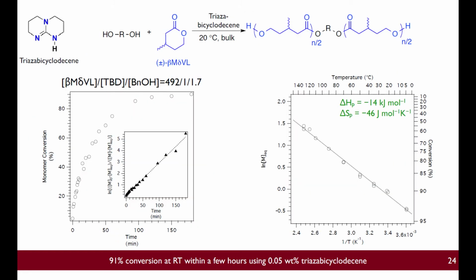Debbie Schneiderman in my group ended up taking beta-methyl valerolactone, and with this organocatalyst triazabicyclodecene, we were able to polymerize the molecule to give this polymer, an aliphatic polyester, with one methyl group here. We studied the kinetics of the polymerization, and we studied the thermodynamics of the polymerization to understand the driving force for getting this polymer and how fast you could get it. And the bottom line is that you can get over 90% conversion within a few hours using a very small amount of catalyst. In fact, we do this in the bulk. We don't use any solvent at all, so this is very conducive to large-scale processing.